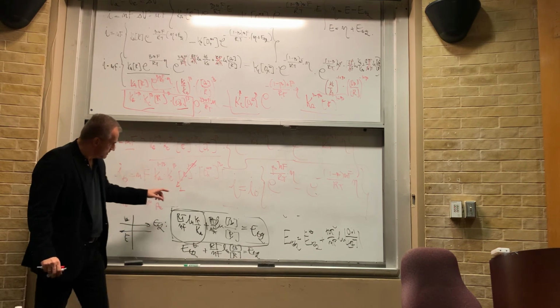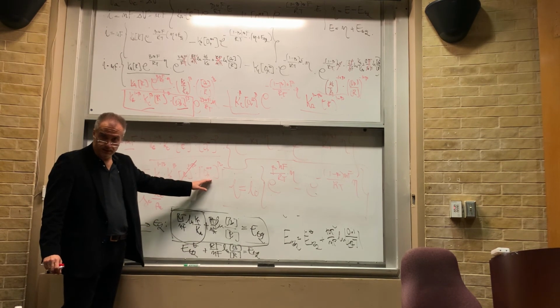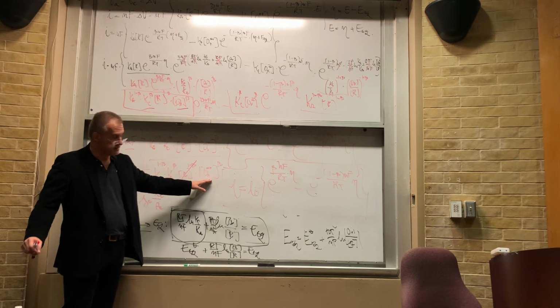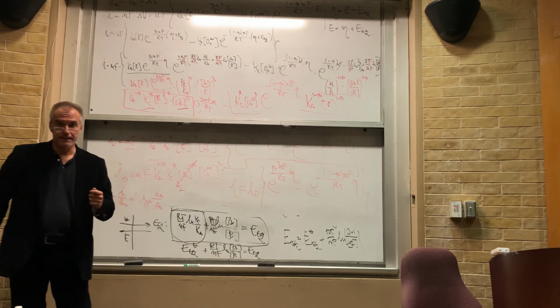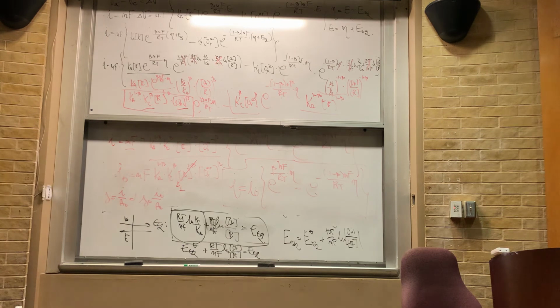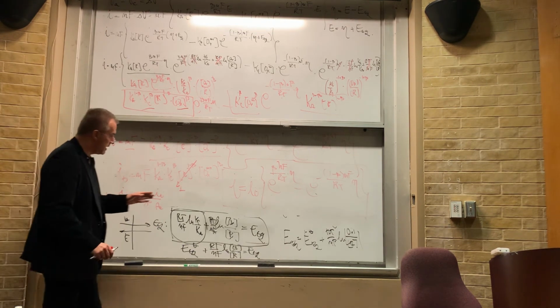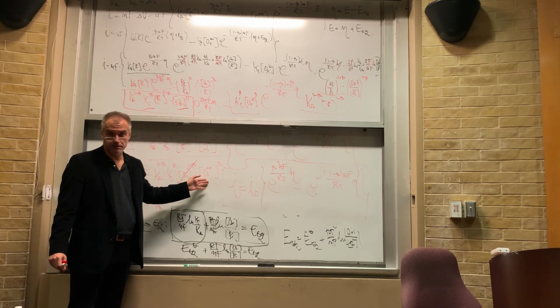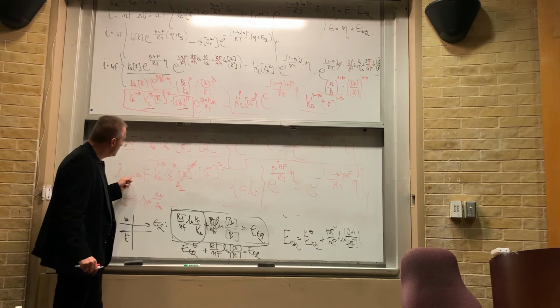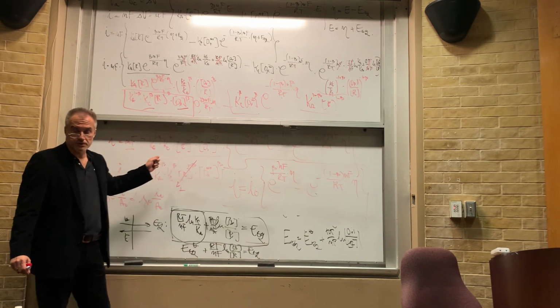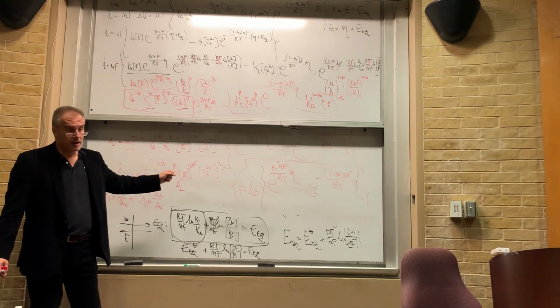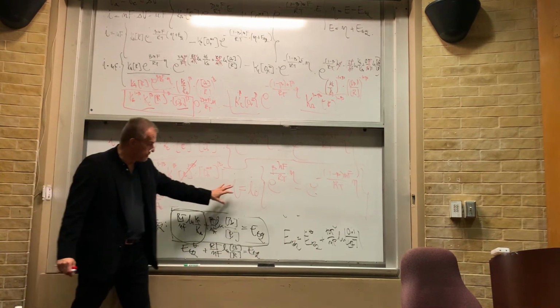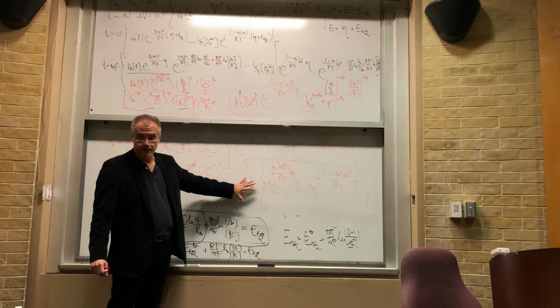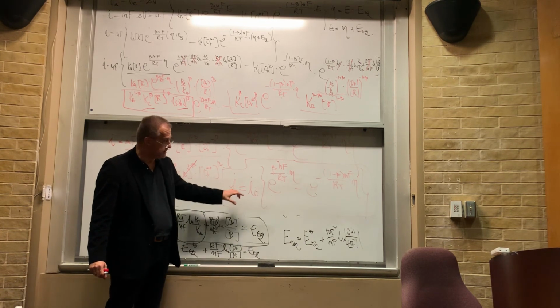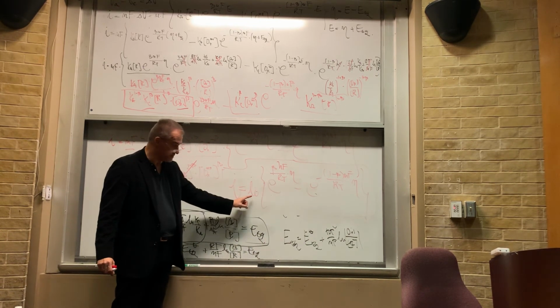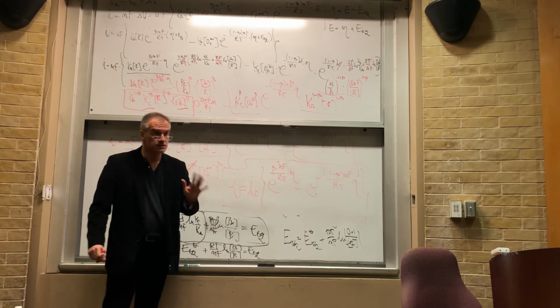However, these constants and the oxidized species, which are copper ions, for example, play an important role in the value of the exchange current density. Which means, if I have a higher concentration of copper ions in the solution, I will have a higher value of the exchange current or exchange current density. By itself, I'm going to have higher activity, or higher current registered as a function of the overpotential, because this exponential factor is larger. That's essentially really important.